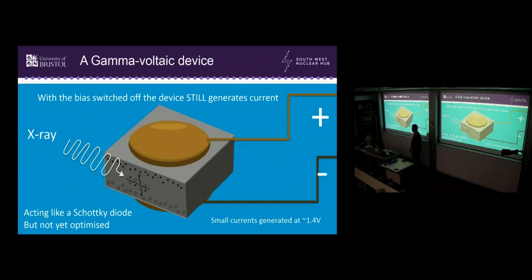And usually we would use the bias to encourage the electron hole pairs which form from gamma interactions to drift to the electrodes to actually produce that current. But it was actually acting on its own. It was acting essentially as a Schottky device, but without deliberately being configured as a Schottky device, because essentially this device was having two ohmic contacts. So essentially the ohmic contacts were allowing electrons to flow freely out of the device with no barrier. But actually it wasn't working like that at all. We were seeing a directionality to the current flow, essentially.